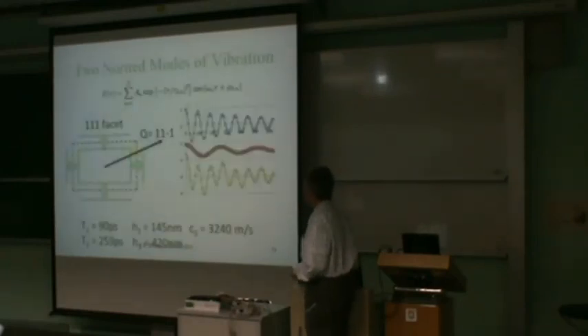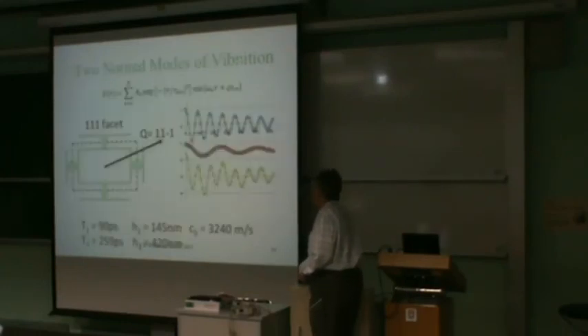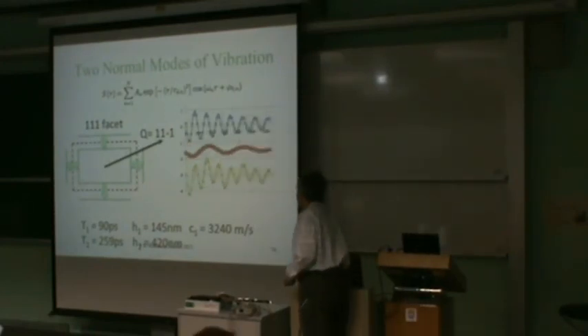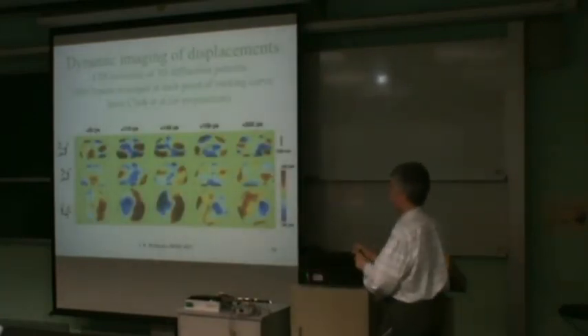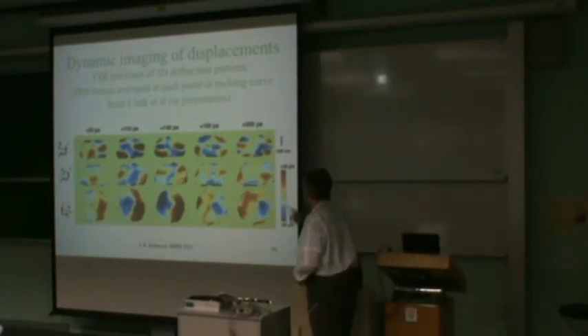Anyway, so we proceed to analyze the position of the Bragg peak, which has got 2 oscillation periods in it. They correspond to vibration modes of the crystal, one in the radial direction, one in the transverse direction. And we can then look at the shape of the crystal after taking out the simple breathing modes of the vibration. We can then look at the next order mode of excitation inside it, which is shown here. X, Y, we've got 3-dimensional images, compression and expansion waves.